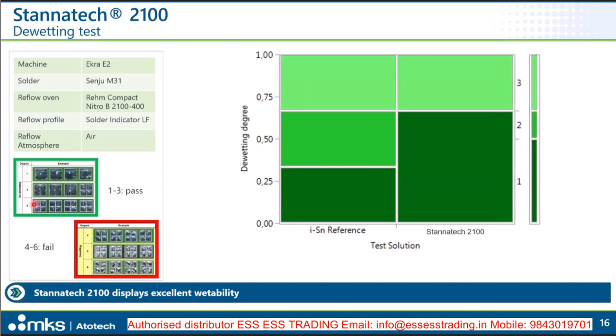We actually distinguish 6 grades of wettability. The first 3 would all be passed. The 4, 5, 6 would all be failed. For grade 1, for example, we have excellent solder wetting, meaning the solder is liquid and connects completely, and the pad is completely covered with the solder. For grade 2, we still have good connections sometimes, but in some of the areas, the printed areas remain as they are.